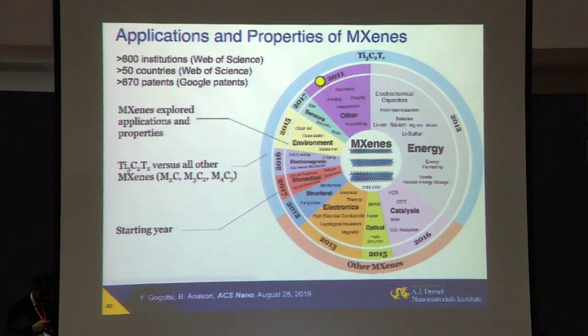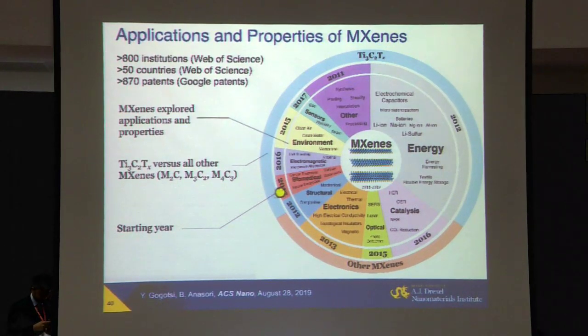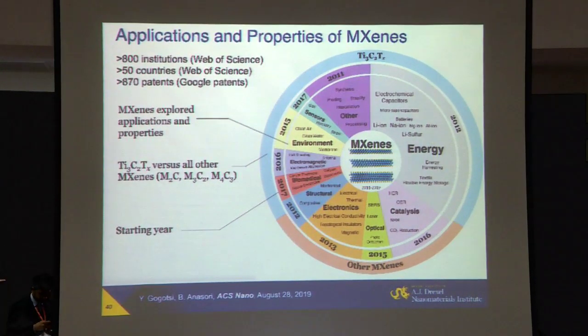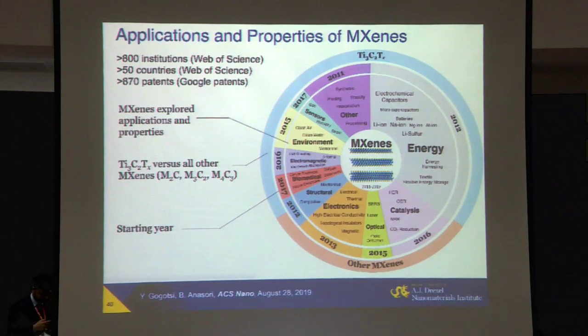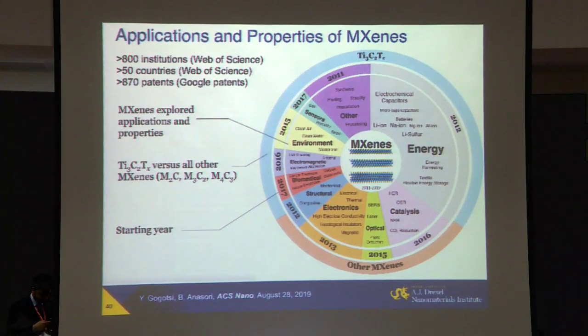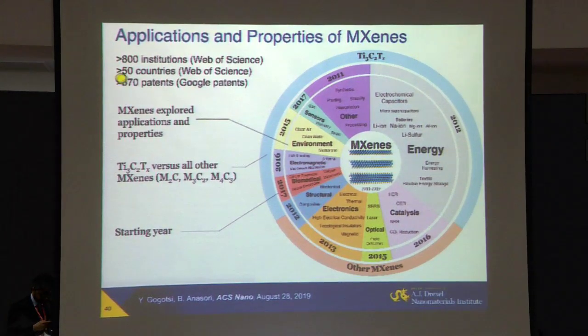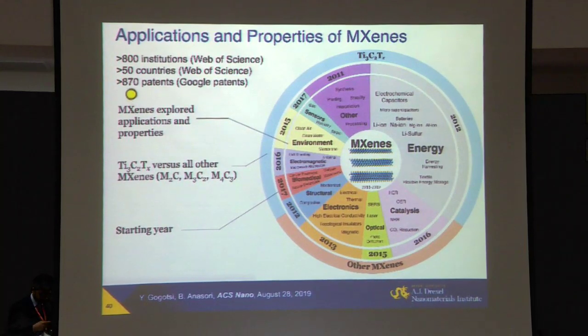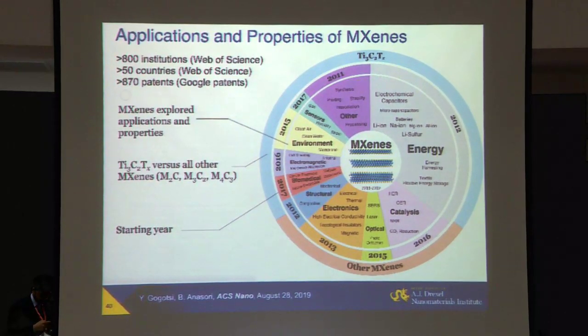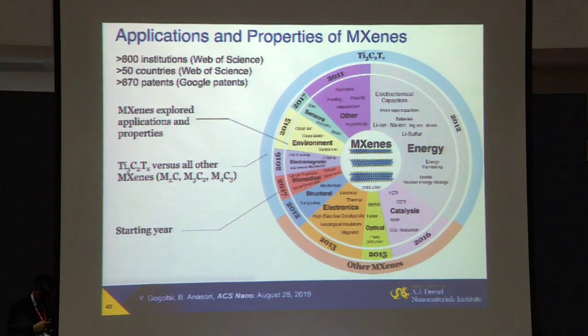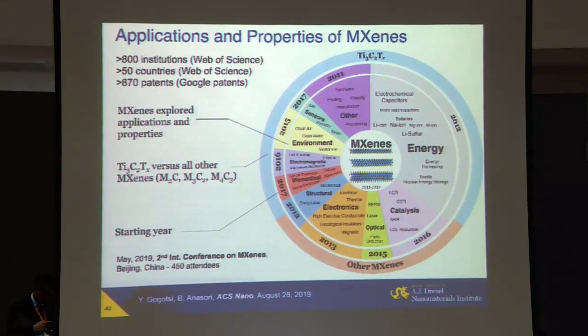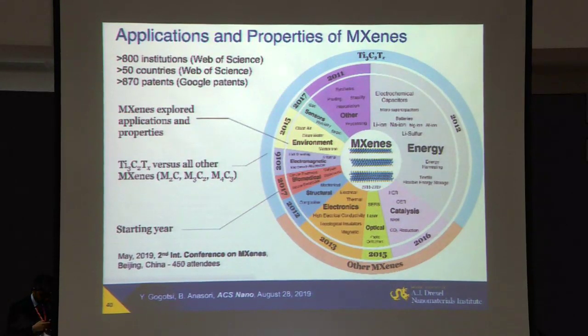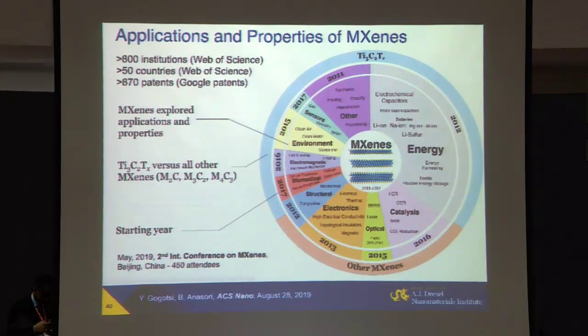Moreover, in many of the fields, like sensors and biomedical applications, the first papers were published just about 2 years ago. So all the results I showed to you are not the result of optimization of the properties of the material. They're the first results available. There is plenty of room for improvement. As you see now, there are already, according to Web of Science, more than 800 institutions from more than 50 countries that published papers. Google Patents shows more than 670 patents filed for these materials. So the field is really growing, exploding. We had 450 attendees at the MXene conference in Beijing in May this year.